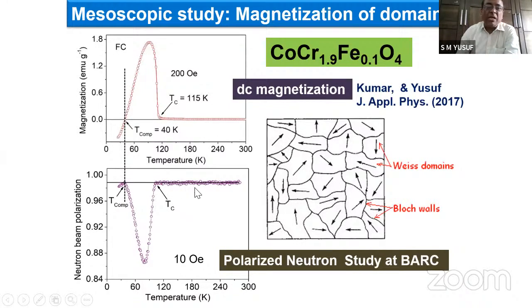In the paramagnetic state, the spins are all disordered, there is no net internal moment, as a result, there is no change of polarization. So the neutron spin cannot rotate. That's why it is the same as the incident beam polarization. But as soon as these ferromagnetic domains are formed at this magnetic phase transition temperature Tc, we see the decrease of neutron beam polarization, because polarization is rotating, and the maximum rotation is where there is maximum magnetization, one-to-one correspondence. And then when the magnetization decreases, the rotation also decreases, so less beam depolarization. But very interestingly, at the compensation temperature where magnetization is 0, the neutron depolarization is 0.